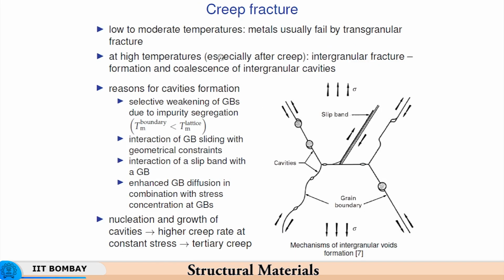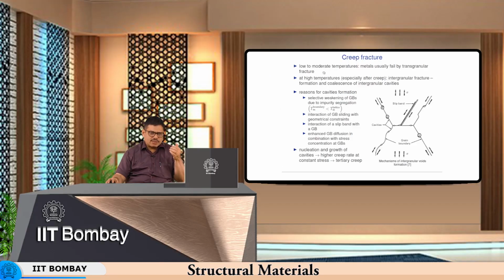Now, creep fracture is the final outcome of excessive creep, and so this has to be avoided. Mind you, you are deforming the material below the yield point. The stress level is below the yield point, and the deformation is occurring purely through thermal effects and time being available. So, temperature, time and activation energy promote diffusion, and this results in plastic deformation in spite of the stress being below the yield point of the material at that temperature. So, we must understand that here there is no yielding taking place the way it takes place in uniaxial tension, but the creep is taking place purely because of the time-temperature dependent flow of material, or physical displacement of material by diffusion.